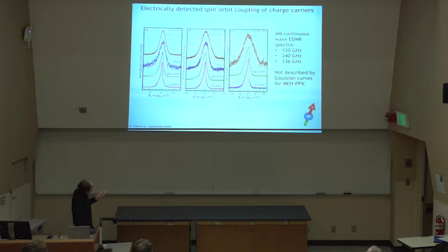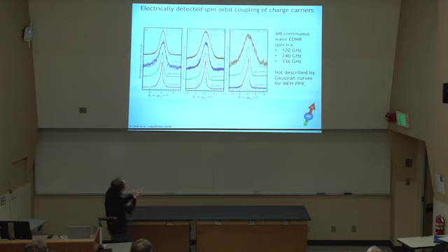line shapes that you cannot straightforwardly explain with this two charge carrier g-strain model, which essentially goes back to fits with two Gaussian functions due to the randomness of this. We've done this here, and you see with PEDOT:PSS it works wonderfully. But with these other polymers, and these are room temperature measurements for these three polymers here, you can't fit that anymore, even though these are functions with great versatility.